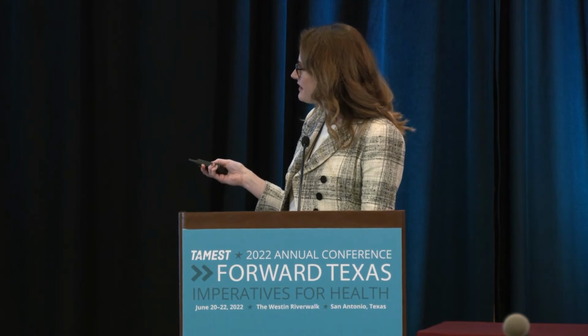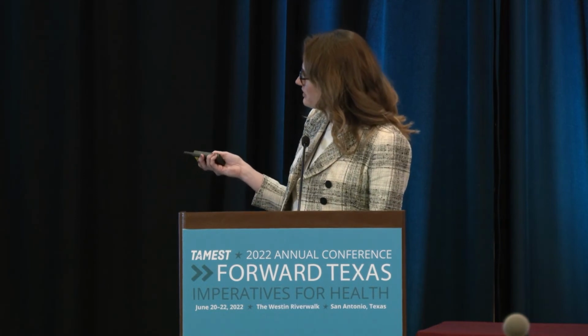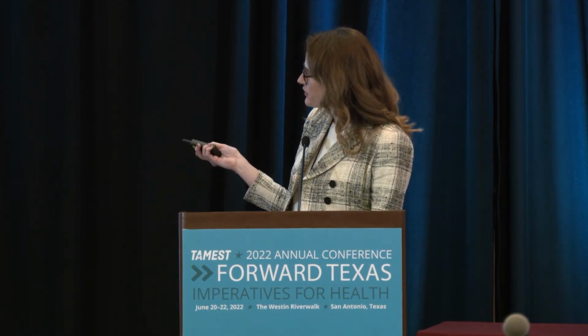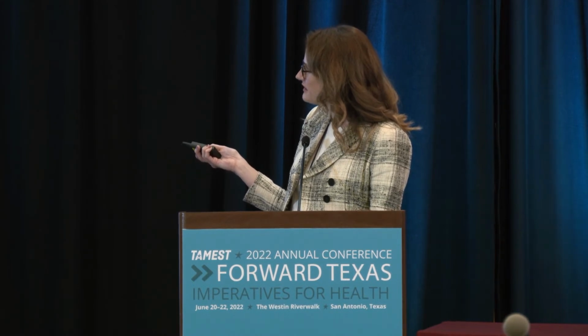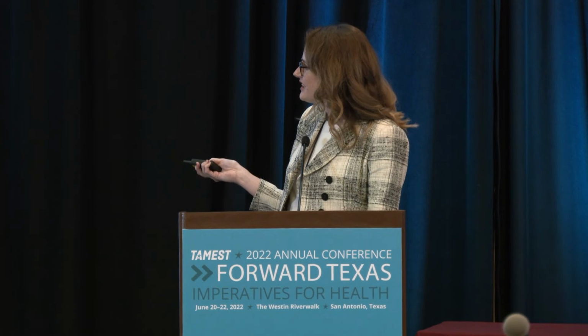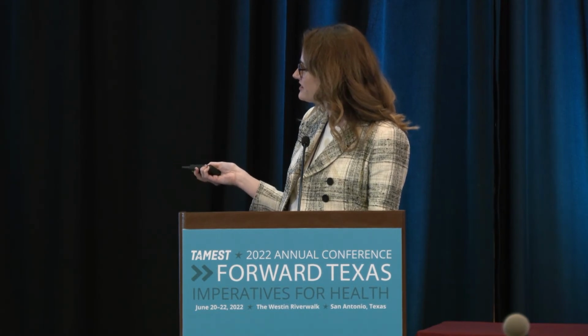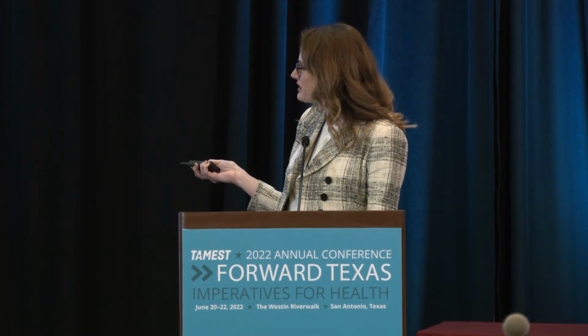And after a lot of thinking and studying the literature, we finally realized the only explanation for how lithium ions could be participating in this reaction is if the polymer electrode itself is swollen with electrolyte. So when we have these organic batteries, we have to think of the polymer as a sponge or as a gel soaked with electrolyte. There's cations and anions in there, and so both of them are participating. So at early states of charge, an anion comes in to balance that first oxoammonium cation, and for charge neutrality, a lithium cation has to leave, so the mass goes down. And then after that process is finished at higher states of charge, the anion comes in to further complete the reaction, balancing other oxoammonium cations that are generated.